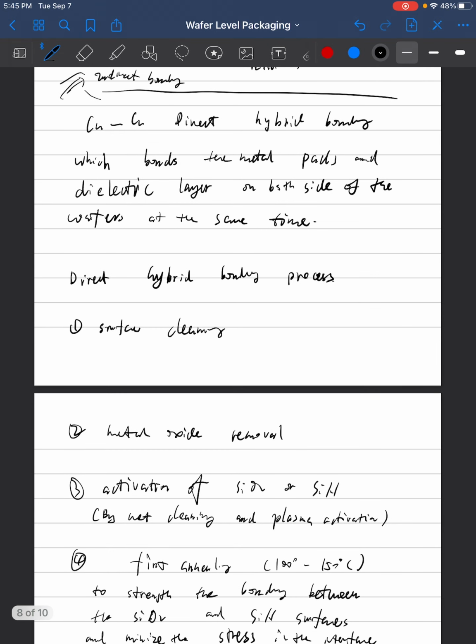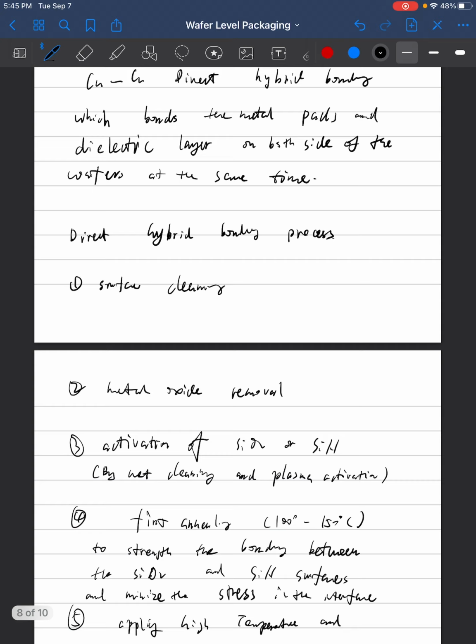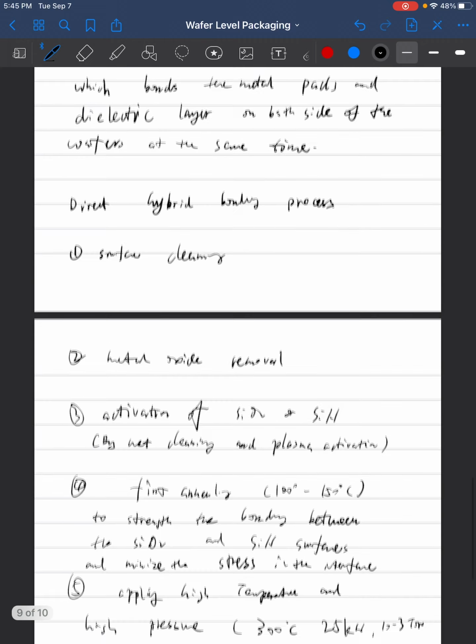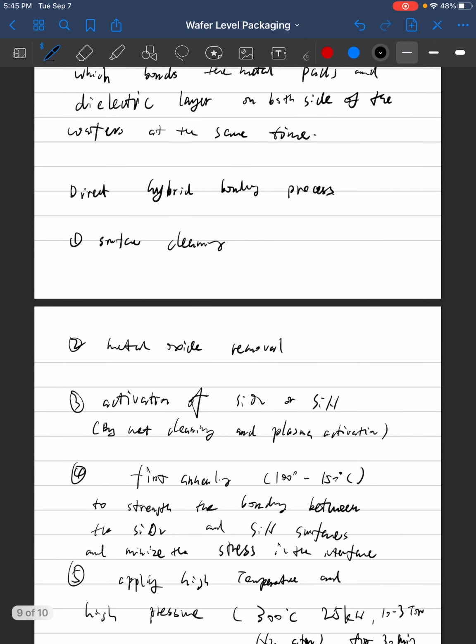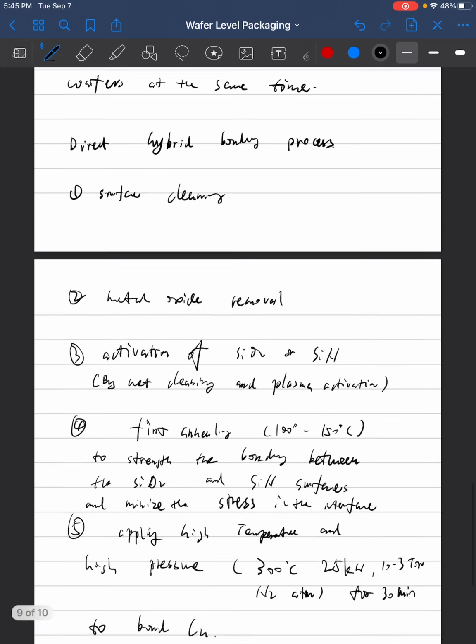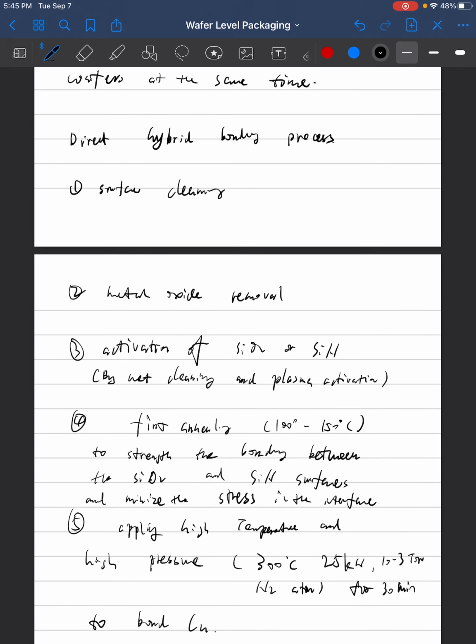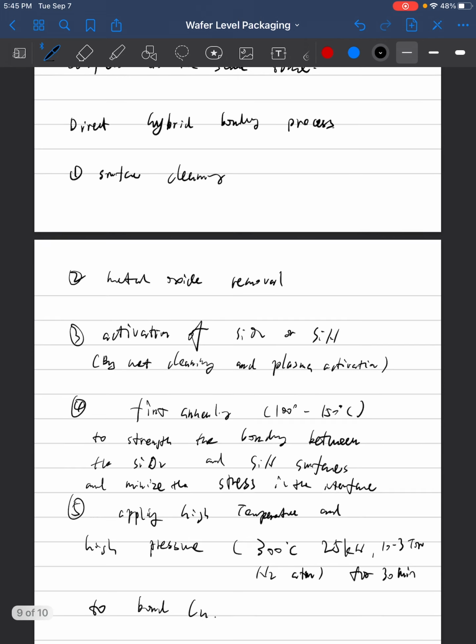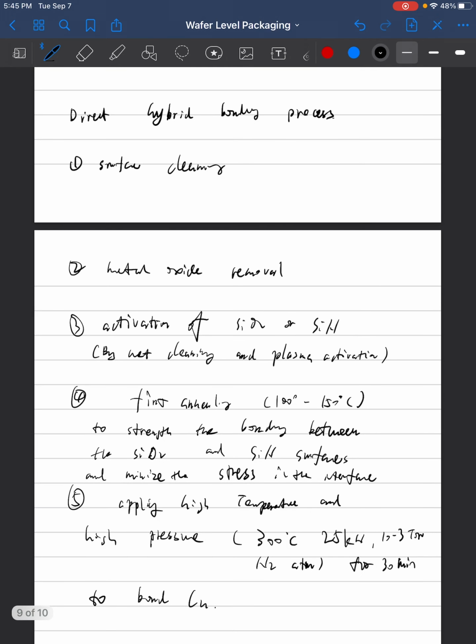First, we clean the surface. Next, we remove the metal oxide so that we have oxide-free copper. Then after that, we activate the silicon dioxide or silicon nitride by wet cleaning or plasma activation. After the activation of the dielectric layer, silicon dioxide, silicon nitride, we do the first annealing at a relatively low temperature, around 100 to 150 Celsius degrees, to strengthen the bonding between the dielectric layers and minimize the stress inside the interface.